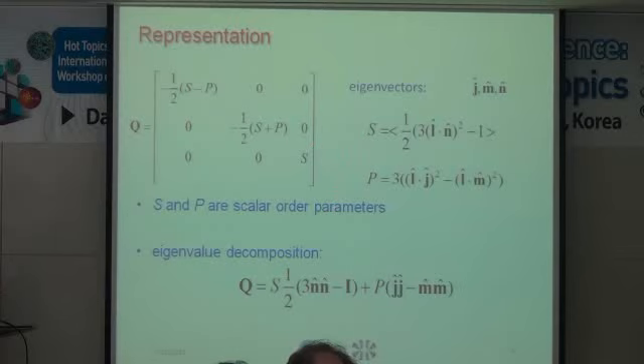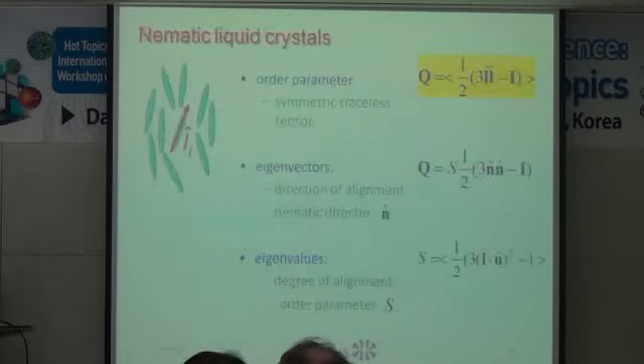And P is a measure of how much symmetry is broken around the preferred direction n hat. So this is a measure of so-called biaxial order. In many cases, P is equal to 0, so in many situations one can ignore this term. Okay, so there's this order parameter tensor, which can be written as a scalar measure of order and something constructed from the eigenvector, which is the direction of average orientation.